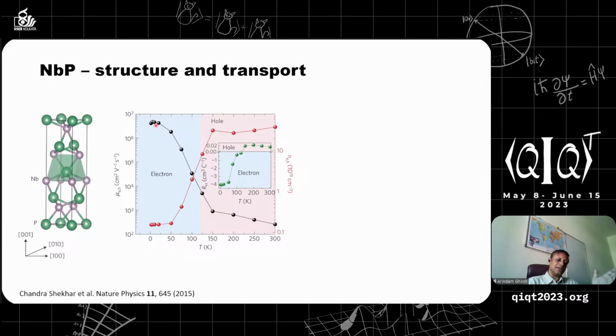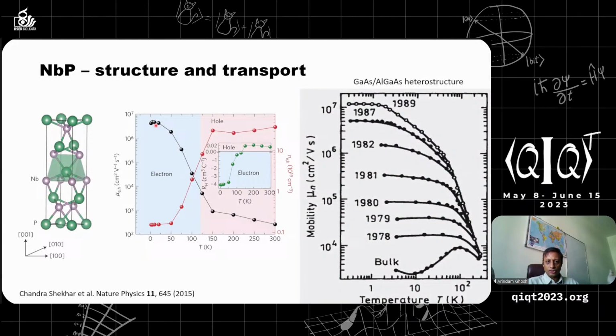If you compare this with, say, gallium arsenide semiconductor structures, which are among the highest mobility semiconductor structures we have today, it took over 30 years to come to the stage of gallium arsenide based mobilities of 10 to the 7. That's because there the mobility is entirely determined by how clean your system is. How disorder-free can you make it? Those are incremental steps we have taken over the last 30 years that have allowed us to get extremely high-quality gallium arsenide heterostructures. But in the case of niobium phosphide, because of the intrinsic protection of the electrons against disorder, you are able to get such high mobilities with relative ease and rapidity.